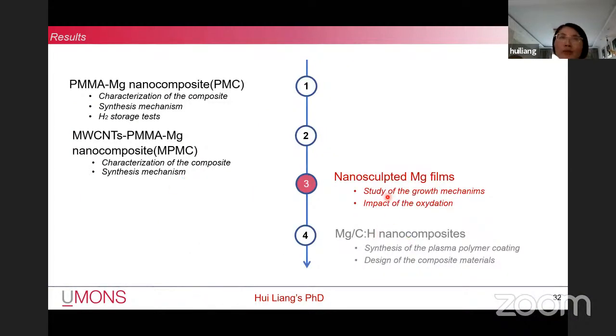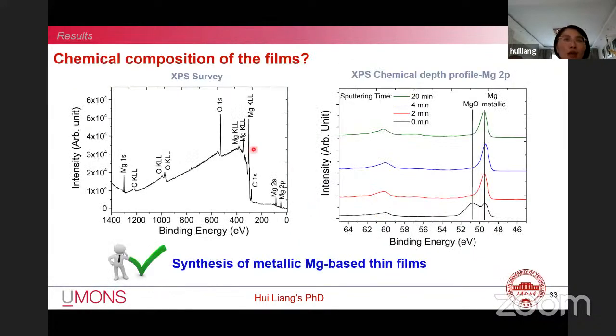Nanosculpted Mg films by magnetron sputtering and GLAD, including the study of the growth mechanism and the impact of oxidation. The chemical composition of the film. In order to measure the chemical composition of the MgC film, we use XPS. Refer to the XPS spectrum for a deposited film, which reveals the presence of the elements Mg, O, and C. It appears that the Mg line is composed of two components, metallic Mg and MgO.